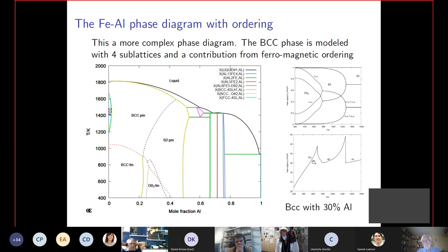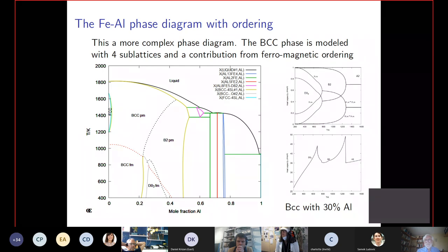You can see the heat capacity curve here. The peak here is the magnetic transition, where you cross the Curie temperature here. Then you have a small jump when you cross from the DO3 to the B2 structure. And this is where you cross from the B2 structure to the A2 structure, the pure disordered BCC. And these are the constituent fractions in the different sublattices. So sometimes the modeling is a bit complicated. And that is basically what interests me, to do the modeling of different types of structures.